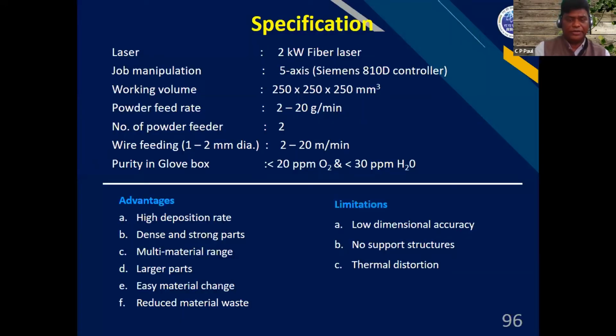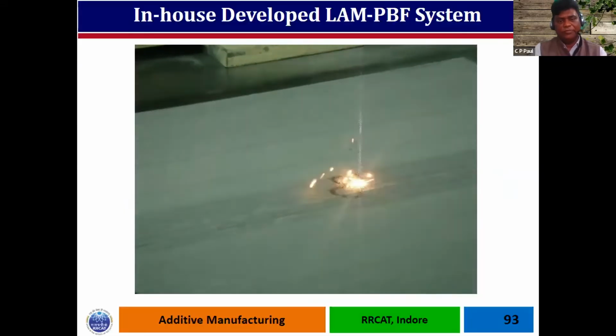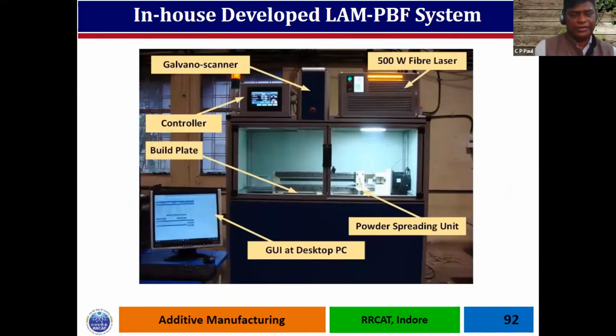Same volume, 250 by 250. We have a 5-axis controller from Siemens 810D, and it can use either wire or powder. Purity in the glove box can be better than 20 ppm of oxygen and better than 30 ppm of moisture. Now, when I talk of building indigenous technology, if you buy this machine from the commercial market, it will cost somewhere around 3.5 to maybe 5.5 crores. And when we built this machine in the country, it is just 1 crore or so.